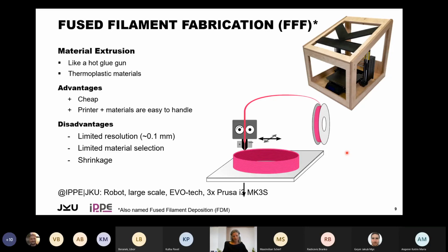And the disadvantages can be named: the layer resolution, which is usually around 0.1 millimeters, but that depends on the die you use. And material selection, well, you can only use thermoplastic materials. And not all of the thermoplastic materials are useful, because when they have high shrinkage or warpage, they don't stick to the platform, and then you have just a mess at the end of the print. Or in general, when you have a lot of shrinkage and warpage, you have a part that doesn't have the required shape from the beginning.